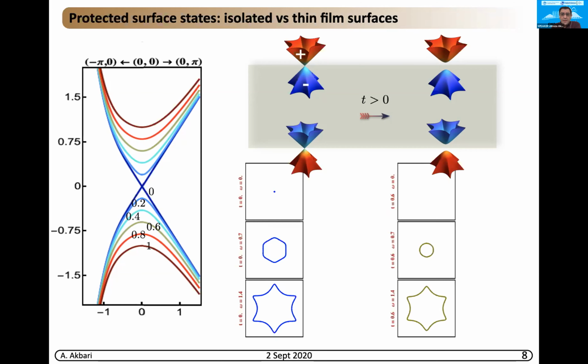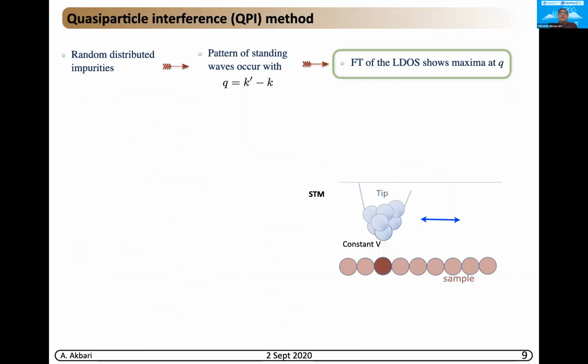Also at finite T, you see that the effect of the gap shows up at lower energy, lower than T, where we don't have any spectral function. Then by increasing the energy above T, the spectral function appears as a small circle and increases with energy, with snowflake features. So now we are ready to look at the calculation for quasi-particle interference.